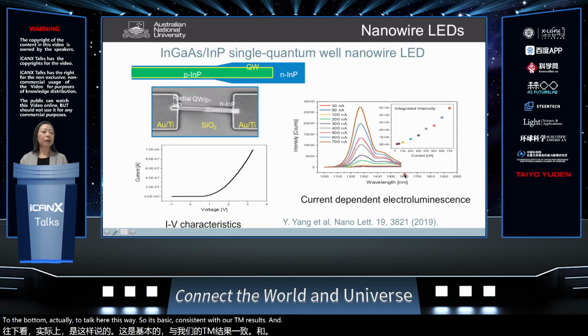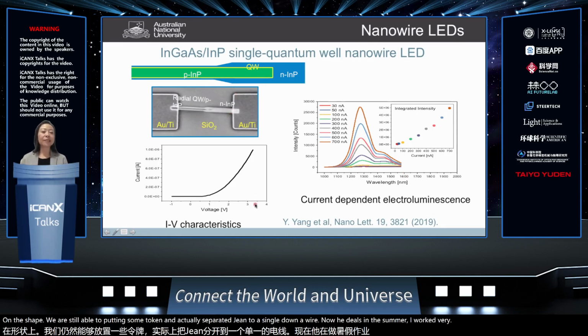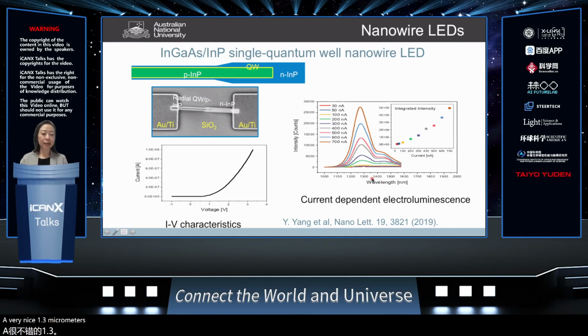And of course, regardless of that not very good morphology and shape, we are still able to put in some doping and actually fabricate single nanowire LEDs, and somehow it works very nicely. It gives out a very nice 1.3 micron light emission as we inject current. So this is just showing that the nanowire material is really quite nice.